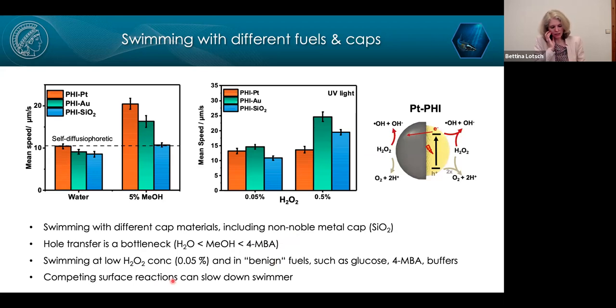Let me just briefly say that we've tested swimming with different cap materials, including silicon dioxide, and we see that even using silicon dioxide, these particles swim. Now we know that even using no cap at all is sufficient to propel the particles if we introduce an apparent asymmetry in these particles simply by shining light asymmetrically, just from one direction. That is enough to propel the particles.